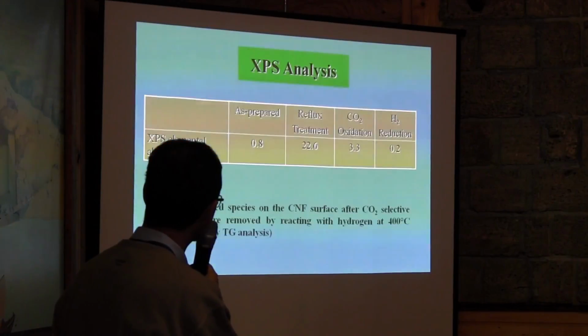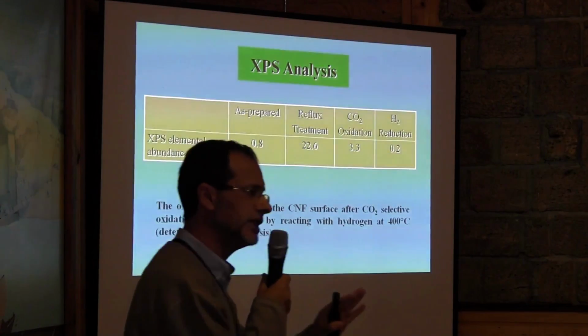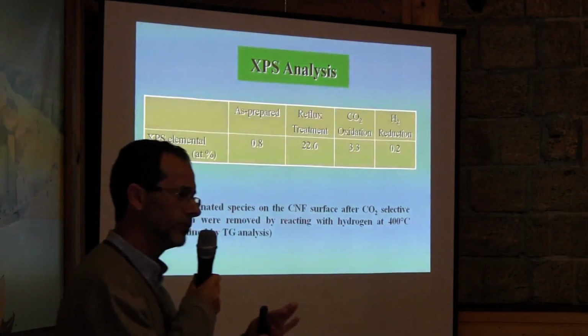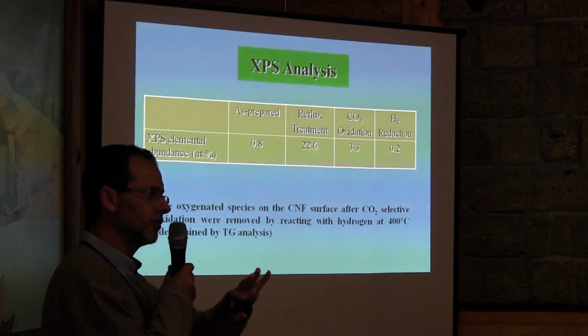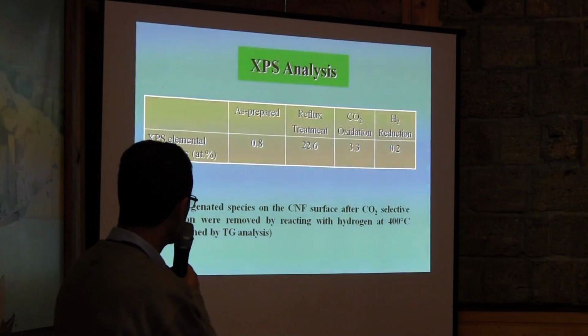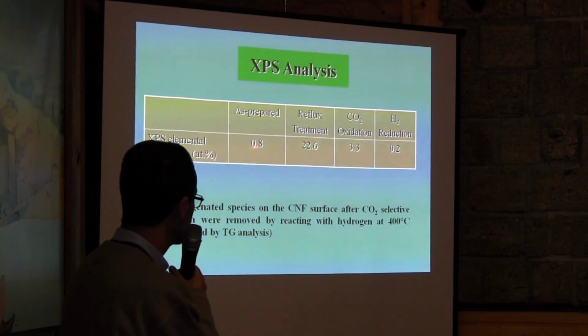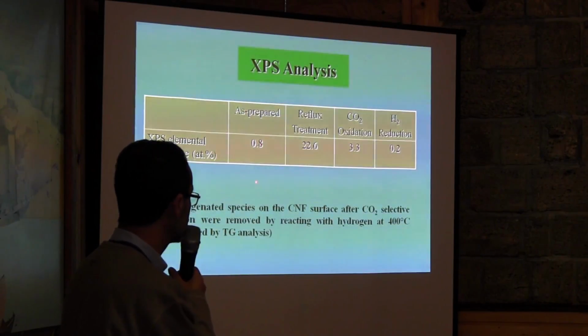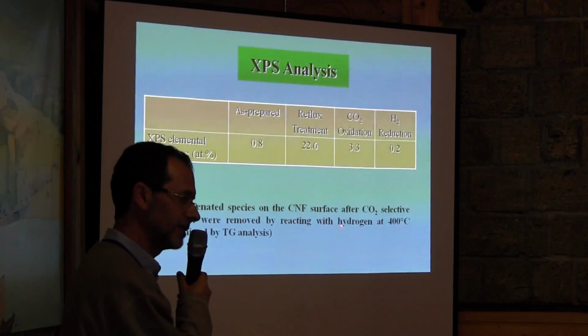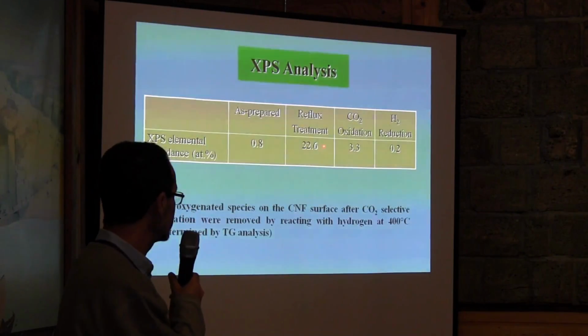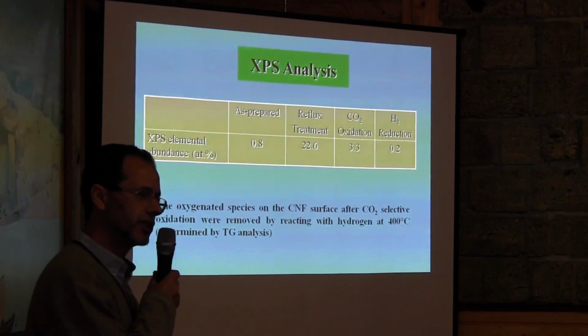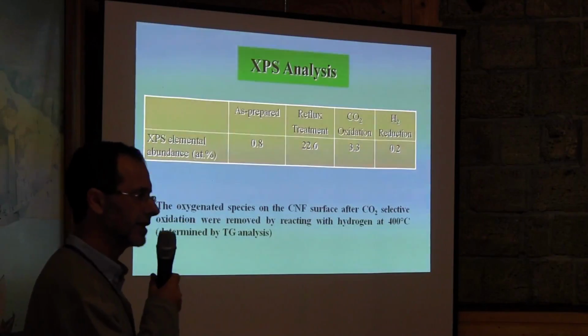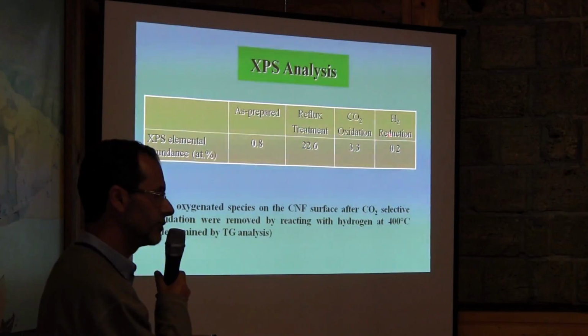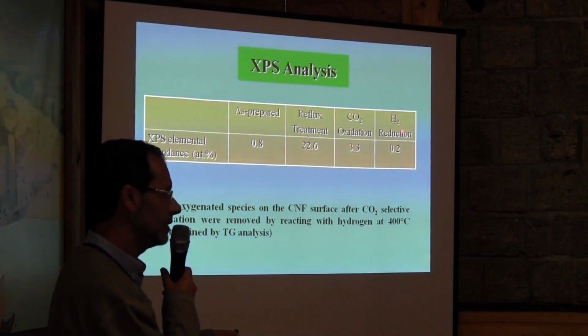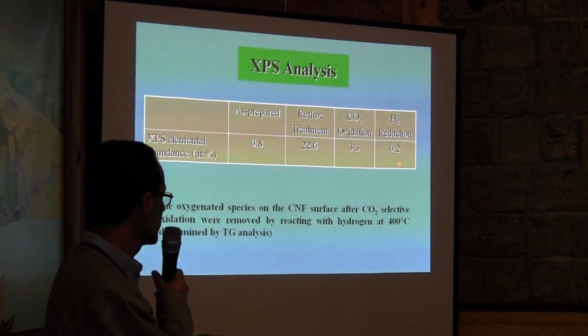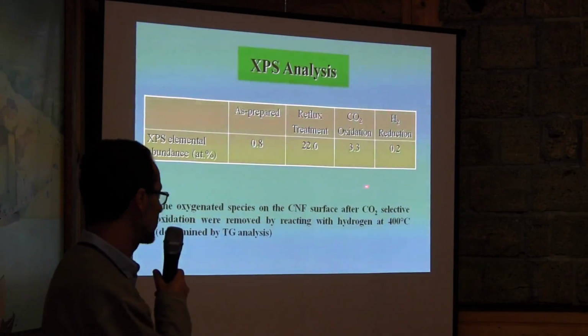Then the next one, okay, now we did XPS because we need to know what we have on the surface. So you can see that as prepared, we have 0.8% of oxygen. When we make a reflux treatment, it's efficient, but it produces a lot of oxygen species on the surface. For me, I don't like that. So when we do CO2 treatment, we have oxygen. Then when we finally do hydrogen reduction, we have the lowest oxygen content.